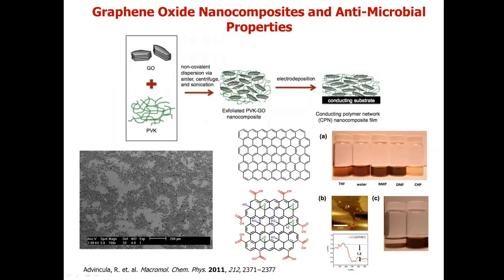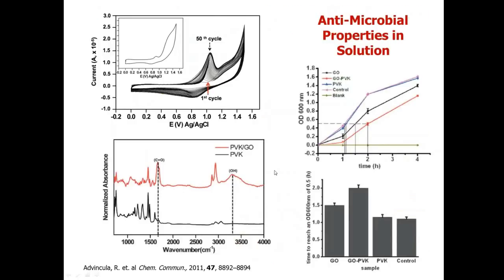In this case, we were interested actually in their antimicrobial properties. So what we did is we took this complex of PVK and graphene oxide, and then we used optical density measurements after exposure to bacteria.